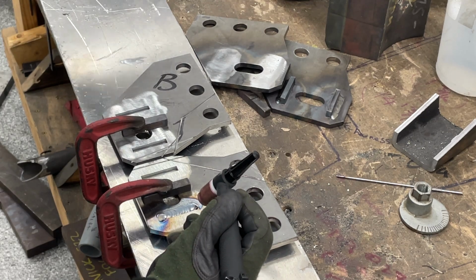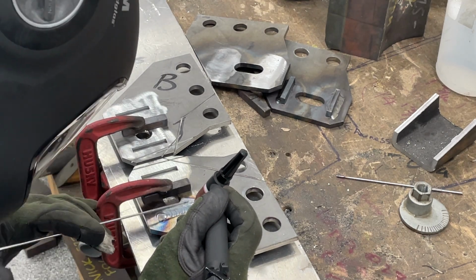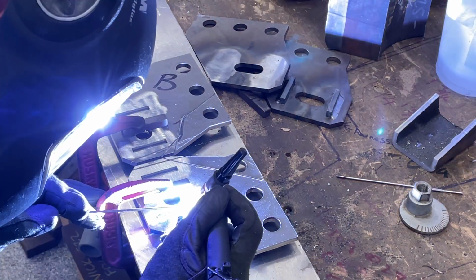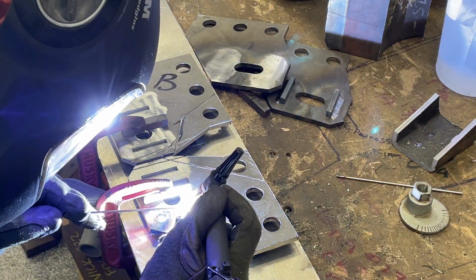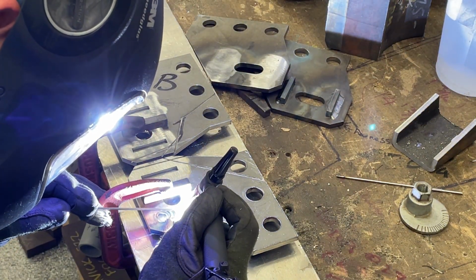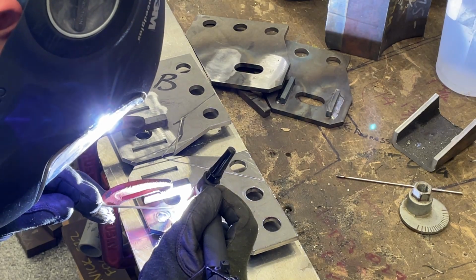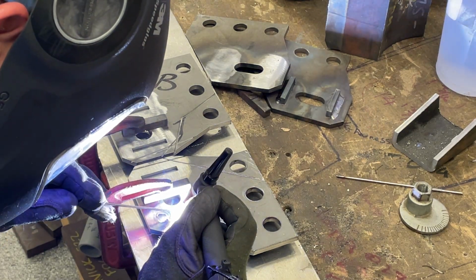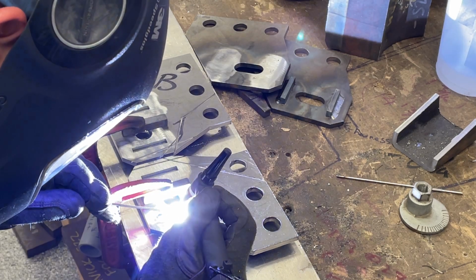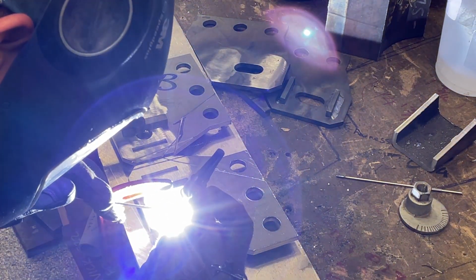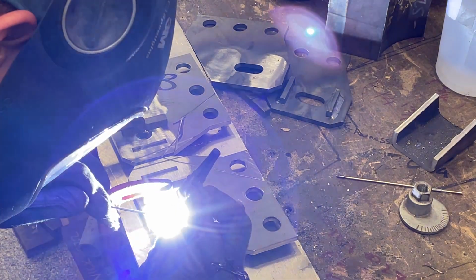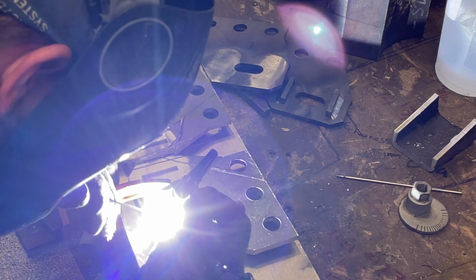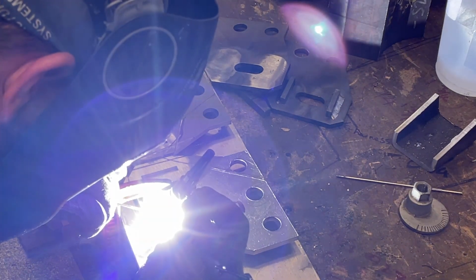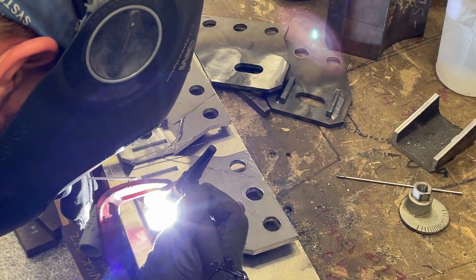Safety glasses are fogging up. All right, here we go. Wait, start, fill it up, go. And make sure to get to the very bottom of the joint. If that means filling in less wire, that's fine. You want good penetration out of this, and keep the tungsten as deep down as you can. If you have a way to measure voltage, it'll be around 10 to 12 volts. Now add wire. Okay, slowly taper off.